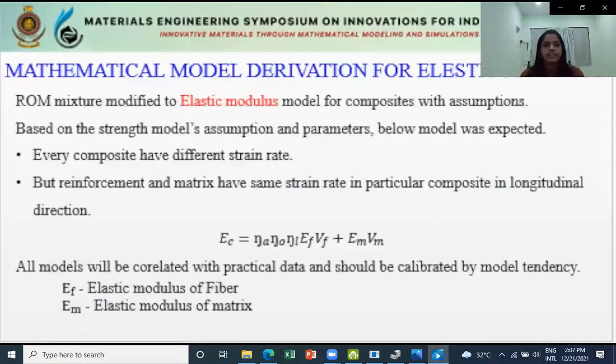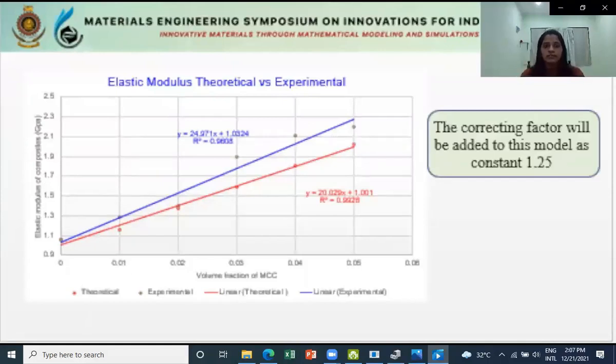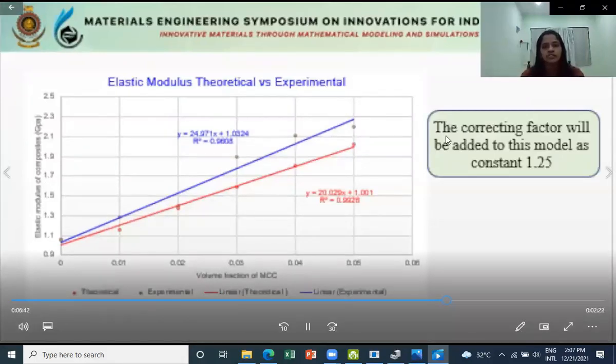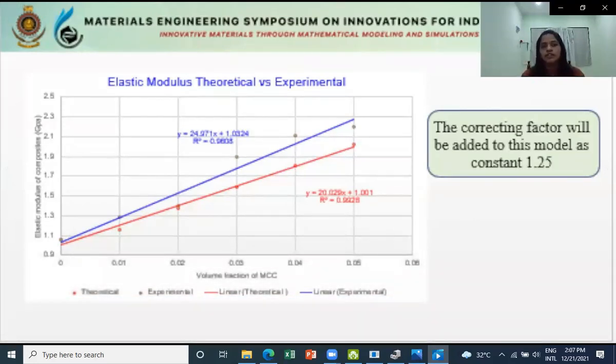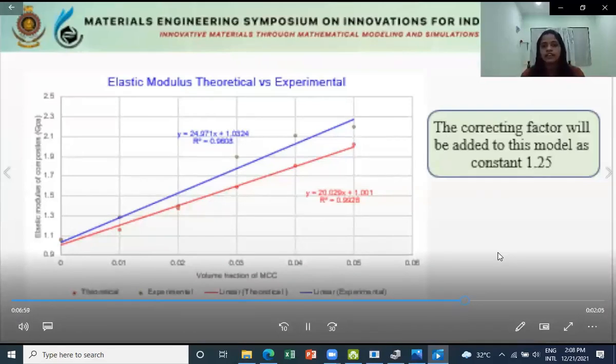Go to the next slide. This slide simplifies the elastic modulus models. The elastic model also has some modification, the same as the tensile model but without the geometrical concern. So the model is affected only by the cellulose part. For the elastic modulus comparison, initial experimental values were less than theoretical values, then exceeded the theoretical values. Here, a correction factor of 1.25 is used to equate the gradients. Then go to the next slide.